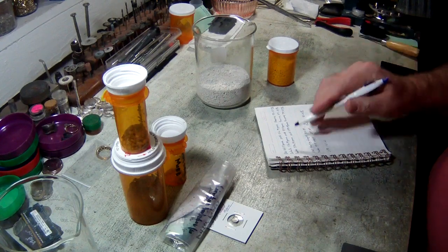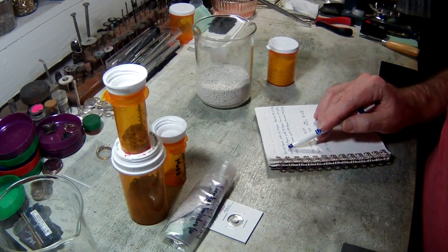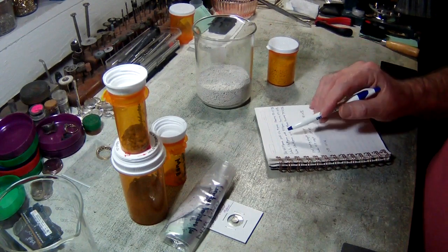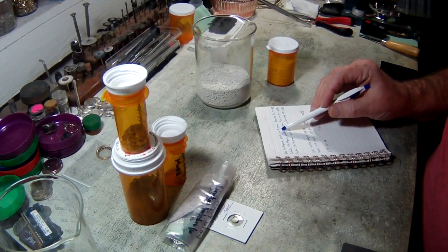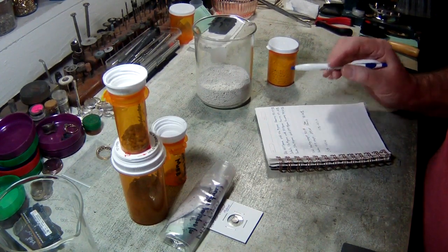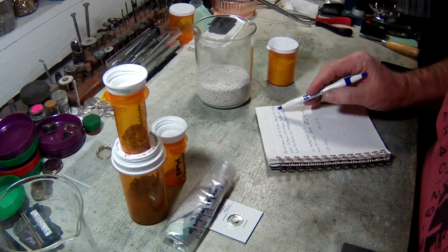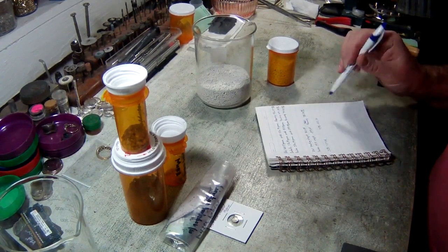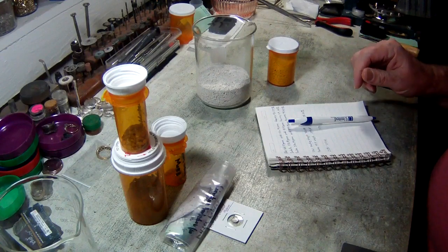In any case, what we ended up with, the blob weighed 168.97 grams. It yielded 156.70 grams of 99.9 silver, which gave us a recovery of 92.57%, which was excellent on that blob.